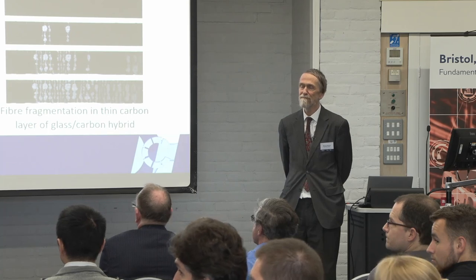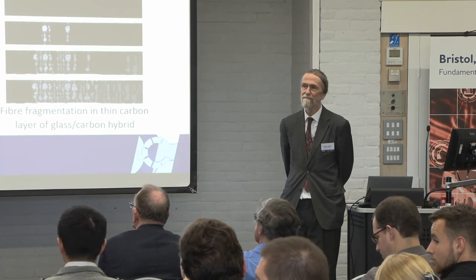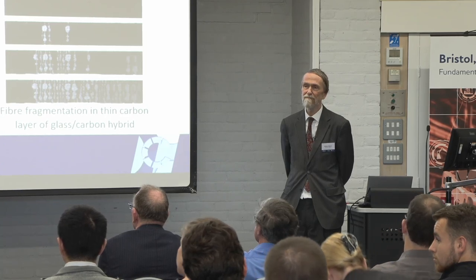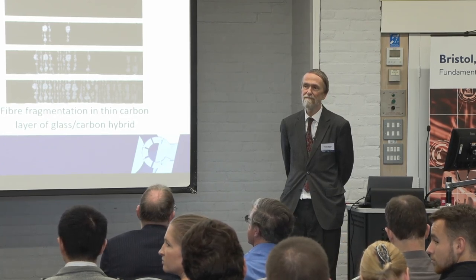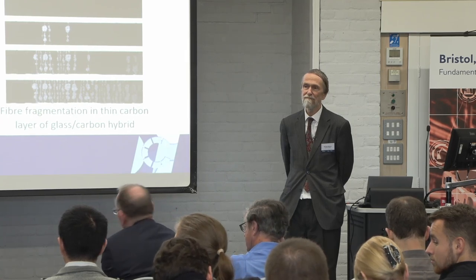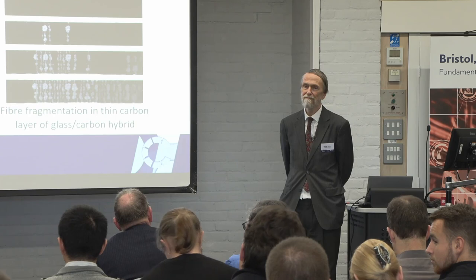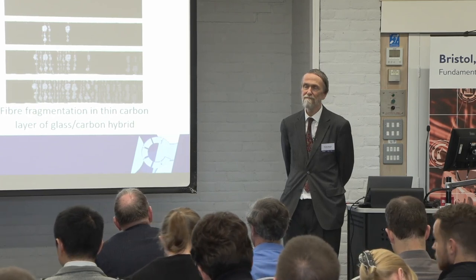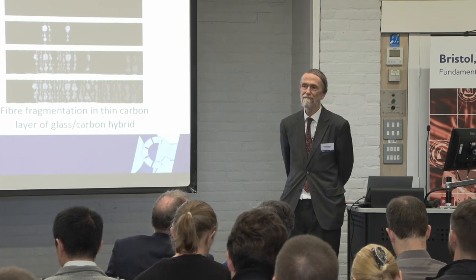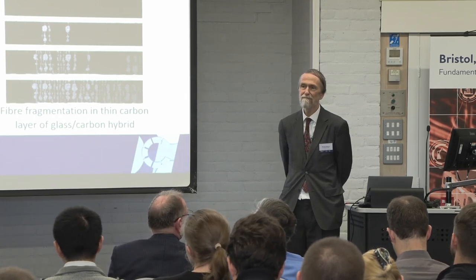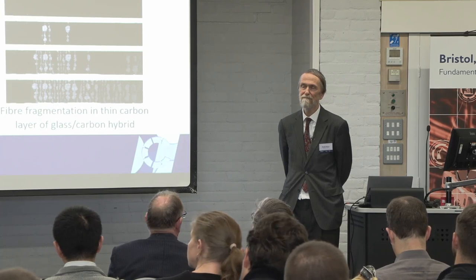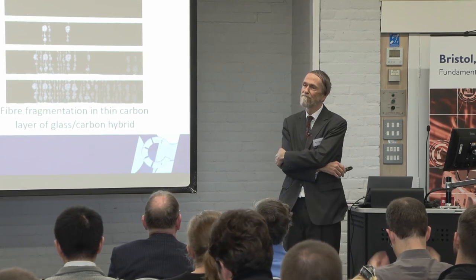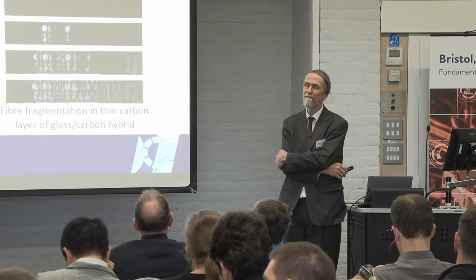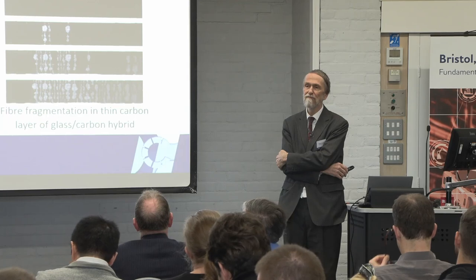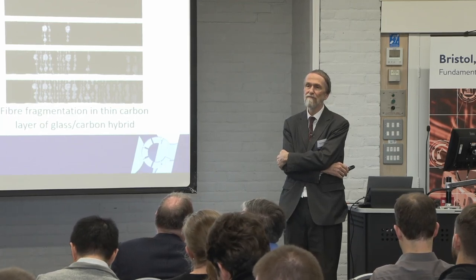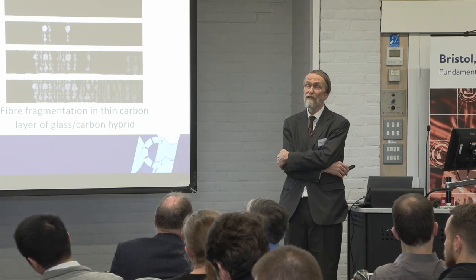Thank you. Very nice and interesting talk. I was wondering if you have tried, for example, to integrate some functional groups in between the layers, like coming from a molecular background. I was thinking if you have more interactions, then possibly you can increase the mechanical stress resistance of these materials, when they are more integrated by some chemical bonding, like non-covalent but supramolecular bonding, like between, for example, carbon and glass. If there are some functional groups which can interact, they can possibly increase the stress resistance of these kind of composites. So I think it's interesting.